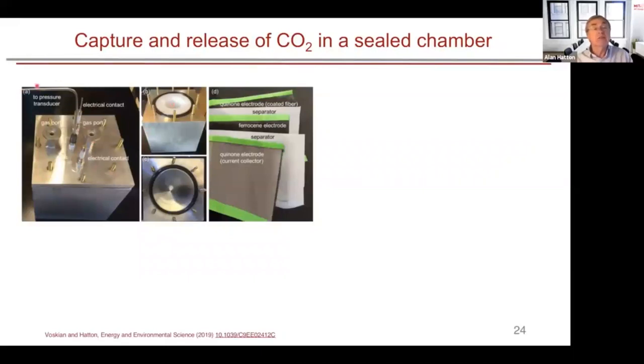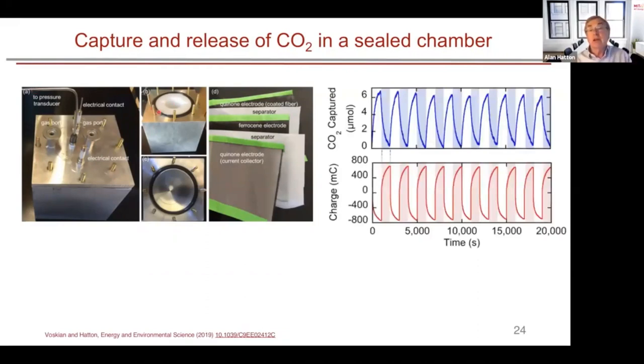As I say, we measure the pressure, and from the ideal gas law we can calculate the amount of CO2 absorbed, and therefore determine the effectiveness of this approach. This will show you what happens in this particular case. Let's just say in this case, we're going from the oxidized to the reduced state of the quinone, and we'll see that when it's oxidized, you get a low concentration of CO2 on the electrodes, the amount absorbed, and when we go up to the reduced state, it gets absorbed pretty quickly and it goes back and forth. And you can see the cyclic efficiency is pretty good in a case like this. So we can go back and forth. We just fluctuated back and forth in terms of the oxidation reduction potentials.